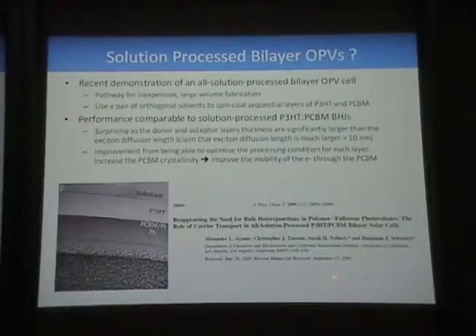In their paper, they reported performance that was comparable to solution-processed BHJ cells. It's a bit surprising as the donor and acceptor layers in their device were significantly thicker than the exciton diffusion length. And they claim that the exciton diffusion length was much bigger than the generally accepted value of 10 nanometers. They attributed the improvement to being able to optimize the processing condition for each layer separately, in particular increasing the PCBM crystallinity, thereby improving the mobility of the electron through the PCBM.